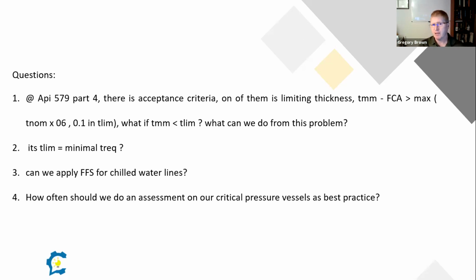So in that case, we really did apply the same methodology in 579 to determine what's happening with that chilled line. And we used that to create new operational guidelines regarding how they cooled that vessel down. I say vessel because it was actually cooling coils on a vessel. Most of the damage was occurring very early in the cooling process. So what they did was they started cooling the vessel slowly at first, brought it down to a little bit lower temperature, and then they used the full cold chilled water to do that. So absolutely, yes, you can apply that.